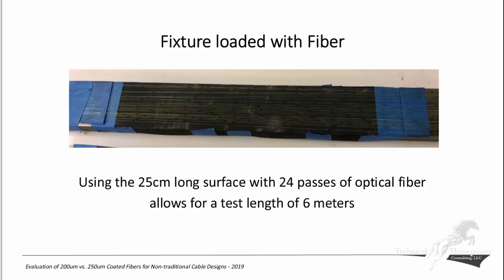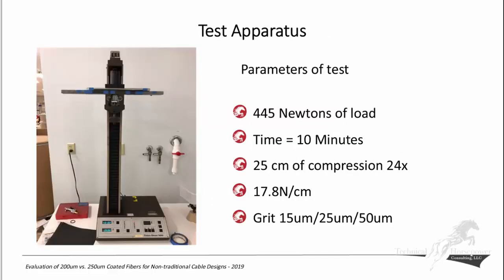Now, that generates a fixture that looks like this. This is our Instron tester. The 2 platens are up there being crushed with 445 newtons of load. Our parameters were 10 minutes of time. So we had 25 centimeters of area compressed times 24 passes, which works out to 17.8 newtons per centimeter. And the grits that we used were 15, 25, and 50 microns.